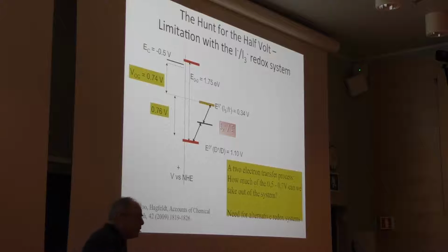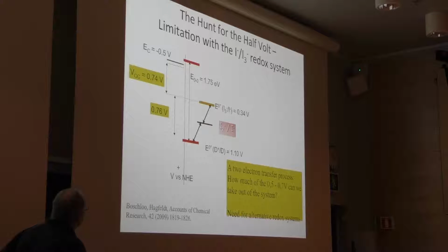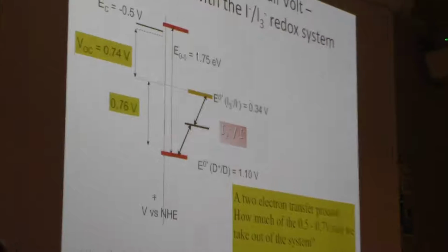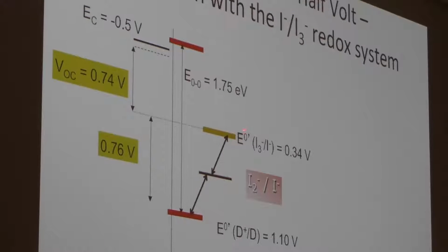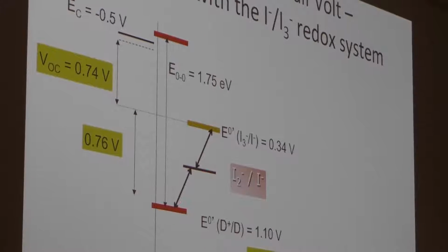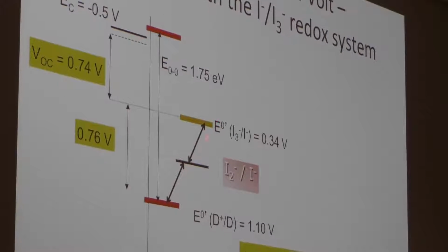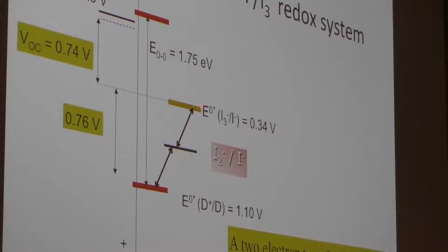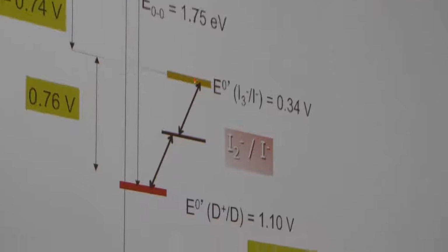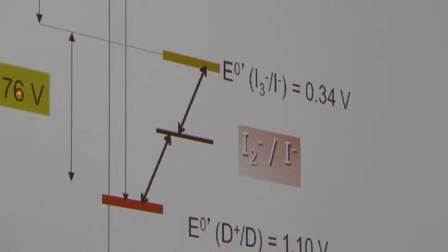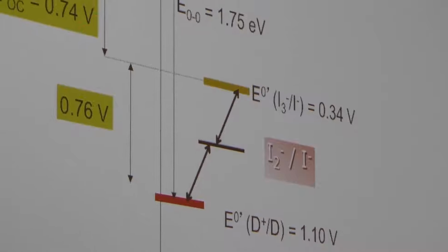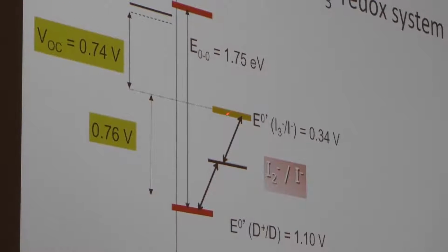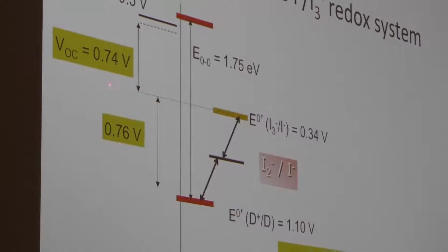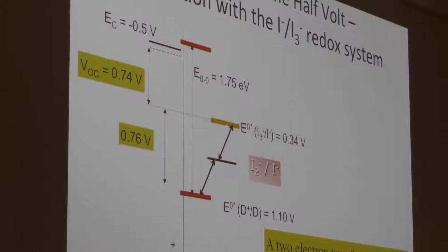And to do that, we need to do some analysis of the conventional system. So this is a simple energy level diagram of the conventional system. Let's say it can be this ruthenium complex. Here is the TiO2 conduction band. You excite, inject, and then you regenerate with iodide, triiodide, and if we draw the energy levels here, we have a redox potential of iodide, triiodide, the oxidation potential of the dye, and here is the big loss in this system. The internal potential drop here is about 0.6, 0.7 volts. The open circuit voltage we get is from the Fermi level of TiO2 and the redox potential of the redox system. So typically 0.7, 0.75 for iodide. But here is the problem, let's say.